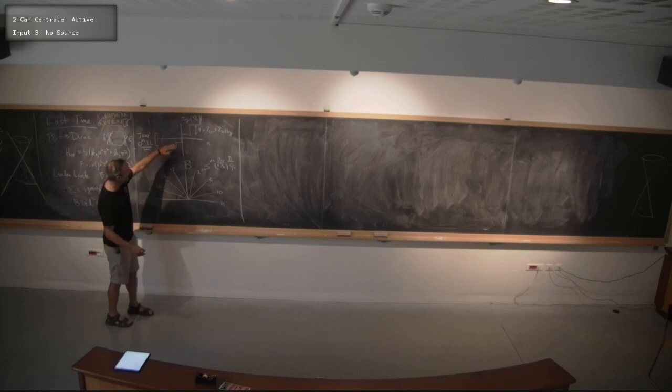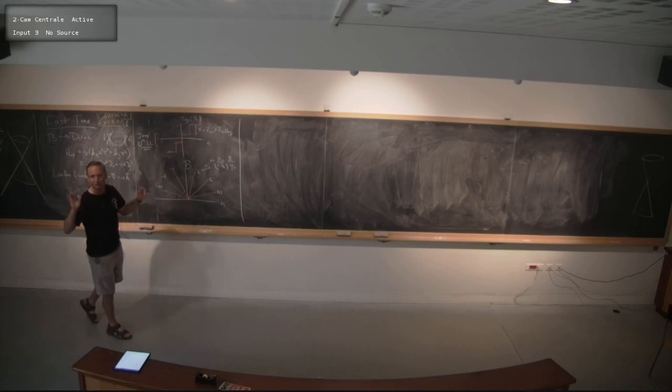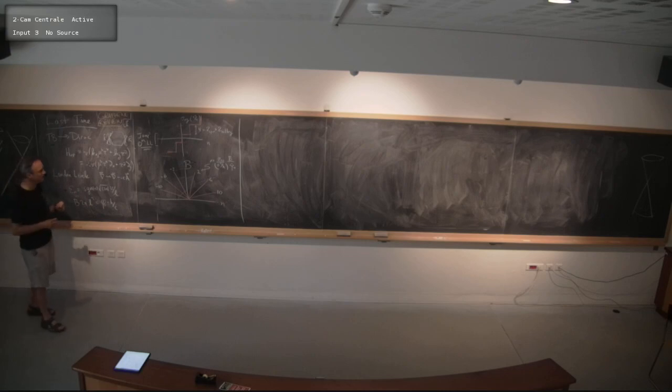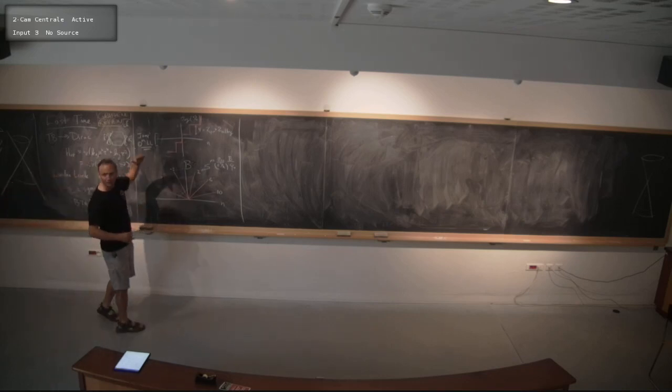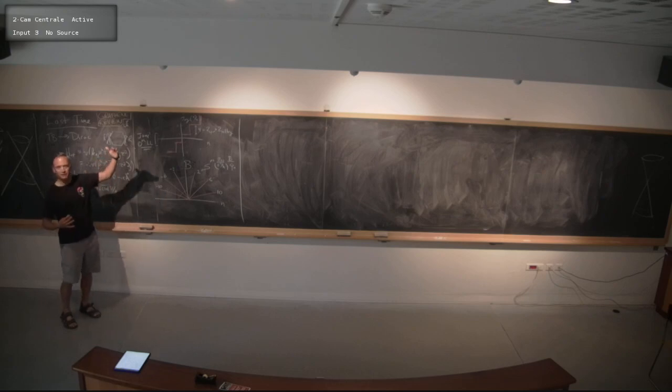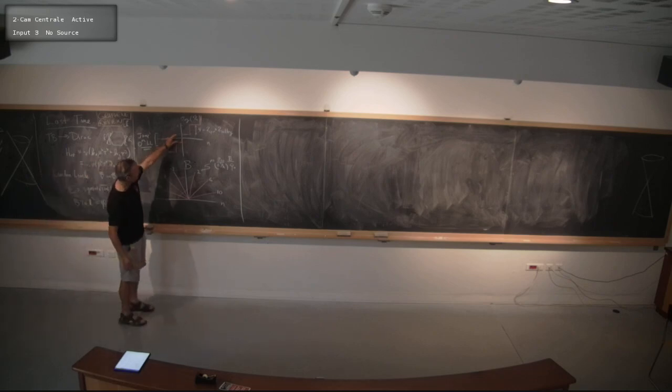The peculiar feature is that at charge neutrality, when you nominally have no electrons, of course we have lots of electrons, there's one electron per carbon atom, but nominally no electrons, you're actually in the middle of a Landau level. So that's not a quantization condition. You have to move a little off to either fill half the Landau level with electrons or deplete half the Landau level with holes. So that jump of 4, which is the same jump as any other Landau level, actually takes you from 2 to minus 2. So this is the most peculiar feature that allows you to identify Dirac electrons in graphene,